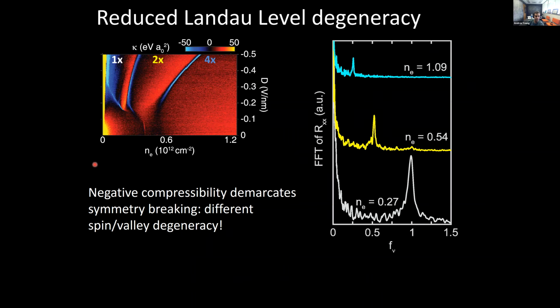So a probe you can do is to look at those same quantum oscillations. Let's take the electron side first. There are 3 different regions at high displacement field, separated by these strong negative compressibility lines. If you take a quantum oscillation measurement and do the same Fourier transform that I described to you, in this region that I'll call the 4-fold region, you see a peak right at 1/4. But in this region, you'll see a peak at 1/2, and in this region, you'll see a peak at just 1.